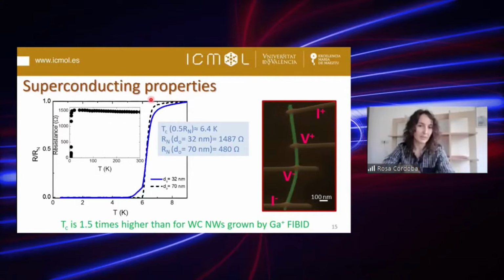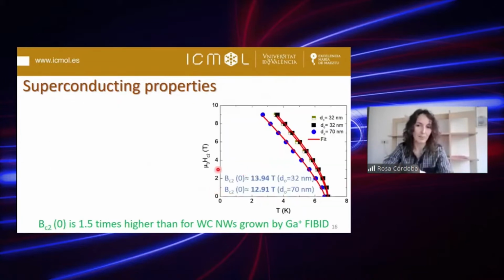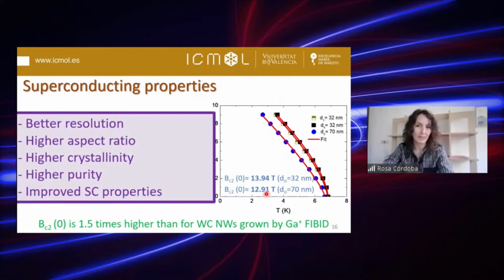Regarding the superconducting properties, we studied superconductive properties of different nanowires with different diameters, and we obtained a critical temperature of around 6.4 Kelvin, and this value is higher than the critical temperature obtained in tungsten carbide wires using gallium focused ion beam. And also the upper critical magnetic field obtained in those nanowires was higher than the values obtained in tungsten carbide grown by gallium focused ion beam. So just by using the helium focused ion beam, we can obtain three-dimensional hollow nanowires with better resolution, higher aspect ratio, higher crystallinity, higher purity, and improved superconducting properties.